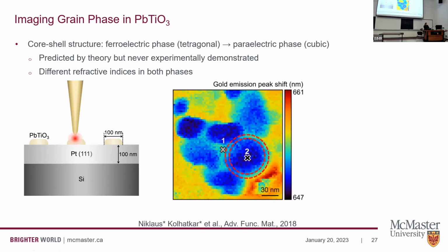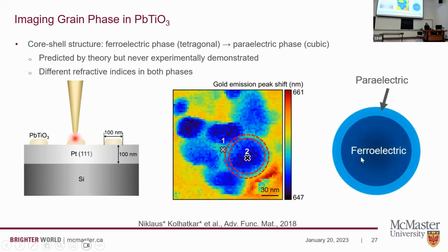So we can see again very clearly the grains that form the nanoisland. Some regions in really light blue on the side, which indicate a change in the refractive index. This confirms that the grains are in the ferroelectric phase, while the shell is in the paraelectric phase. This confirms that with this technique, we were able to image the different phases in the nanograins with a very high spatial resolution, down to 30 nanometers.